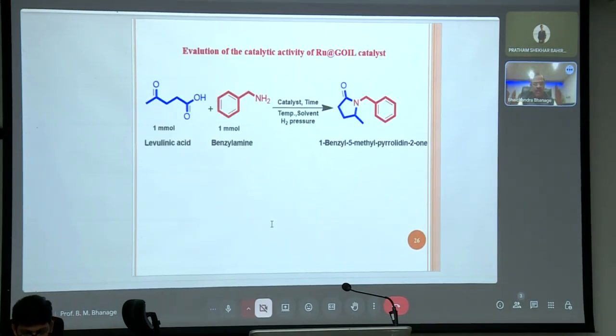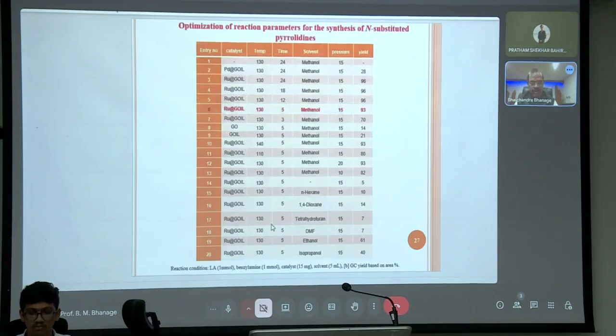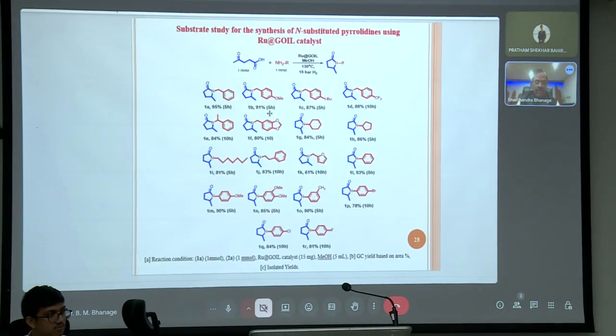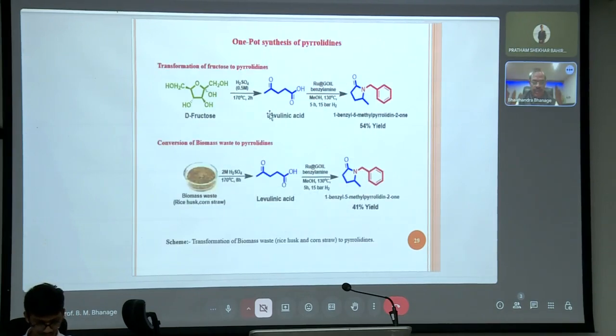You take levulinic acid, react that with benzylamine, and as I told you, the ruthenium GO-IL catalyst can give you the reductive amination followed by the cyclization. So we screened several catalysts in this particular case, and we optimized this particular catalyst, that is ruthenium GO-IL. A 93% yield can be obtained at 15 bar in 5 hours at 130 degrees centigrade. You can see that a number of such substances we have prepared using this technique, and many of them were novel compounds. We have well characterized them, and you can get more details in the publication.